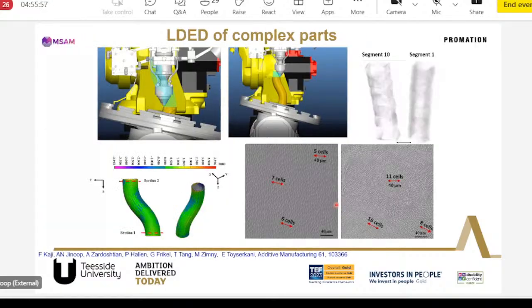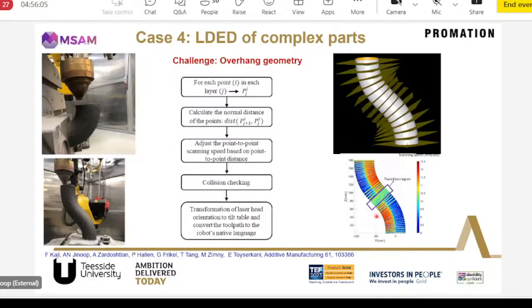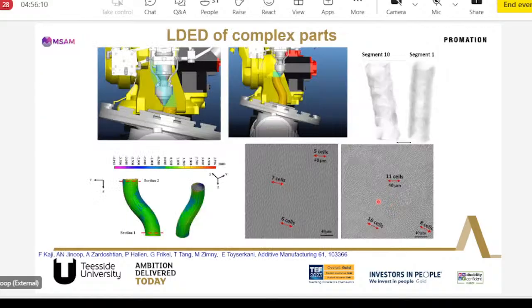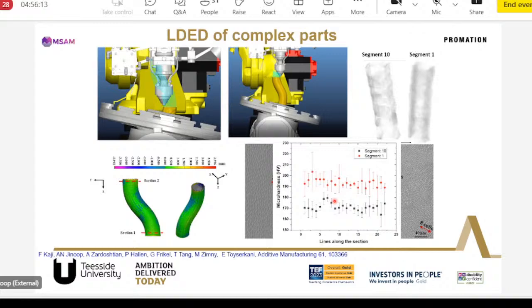So there is a slight variation in the grain structure. The area which has a higher speed has got a finer grain structure, but the area with the lower speed has got a coarser grain structure. You can see the difference here, but the impact on the hardness is not very obvious, I will say. It's not very high. So you can see how the variation has happened. The fine grain structure area has got a higher hardness. The larger grain structure area has got a lower hardness. But again, the variation is within the range that we are expecting.